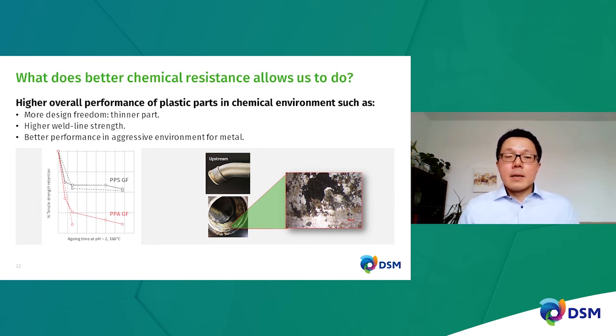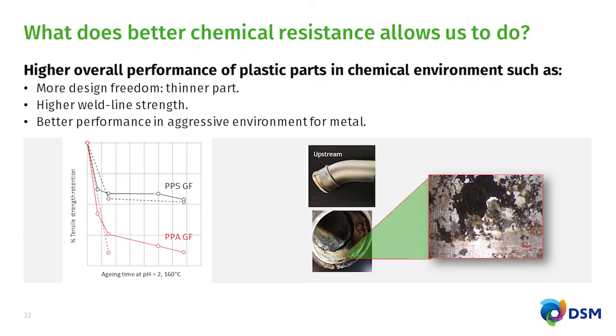We also have the ability to use these high performing grades to make sure that we have higher weld line strength. So this is particularly important if you are considering the glass-filled polymer grades with a lot of weld lines. And as you know, in the weld line, typically the strength is not determined by the glass fiber matrix interface, but intrinsically by the properties of the polymer itself. So if you have a polymer that is resistant towards degradation in that chemical environment, then it also translates to increased weld line strength.